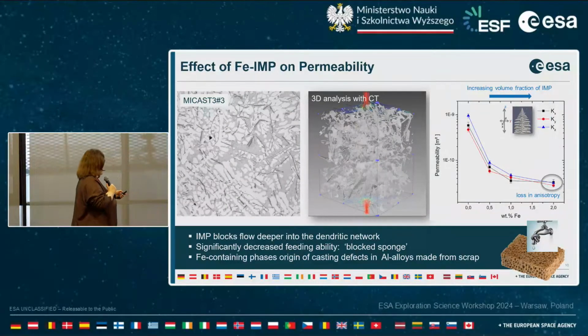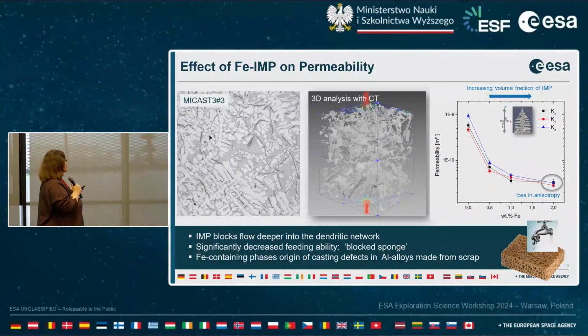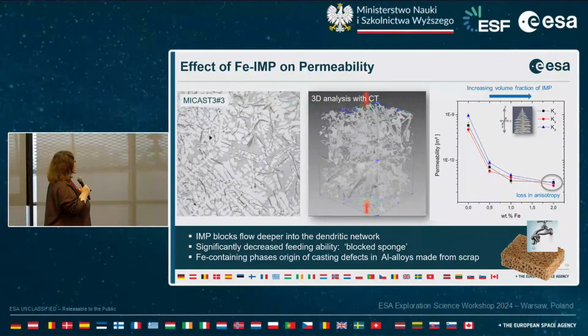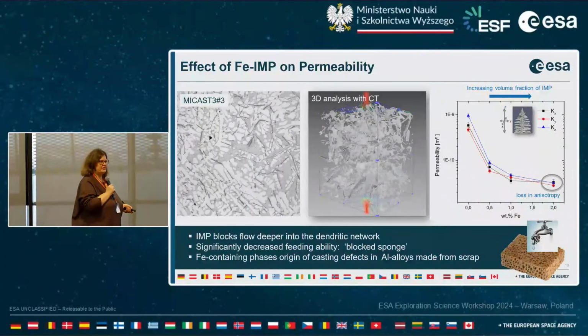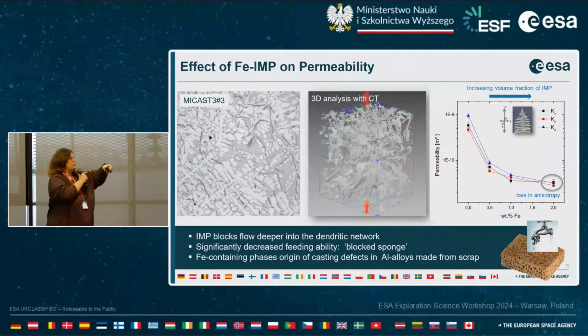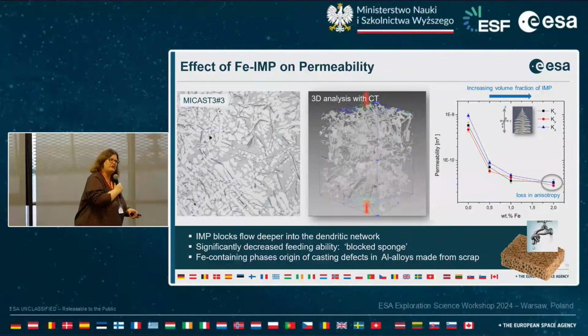So therefore, just go back. Here you see a typical microstructure of such a sample in 2D, MICAST3#3. The light gray or white phase here are the dendrites, in the matrix and eutectic, and here you see again, it looks like needles in 2D, the beta intermetallic phase, the iron-containing phase. But when you think about a needle, when you look at the top of the tip of the needle, you should expect some black dots here, but you don't see anything. So therefore, we put the sample sections in our computer tomography to analyze the sample structure in 3D.